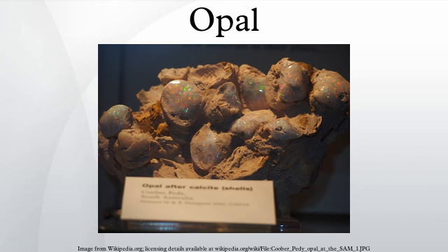The structure of low-pressure polymorphs of anhydrous silica consist of frameworks of fully corner-bonded tetrahedra of SiO4. The higher-temperature polymorphs of silica, cristobalite and tridymite, are frequently the first to crystallize from amorphous anhydrous silica, and the local structures of microcrystalline opals also appear to be closer to that of cristobalite and tridymite than to quartz. The structures of tridymite and cristobalite are closely related and can be described as hexagonal and cubic close-packed layers. It is therefore possible to have intermediate structures in which the layers are not regularly stacked.